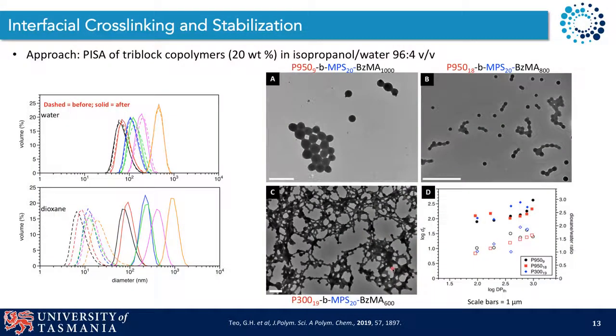A secondary approach to attempt to do this was to use, again, the PISA method to polymerize or form triblock copolymer nanoparticles, again with an MPS functional interface. And again, before and after cross-linking, what we were able to see was good correlation of the particle size distributions in both water and dioxane, with a dissociation back to the unimer state prior to the cross-linking procedure taking place.